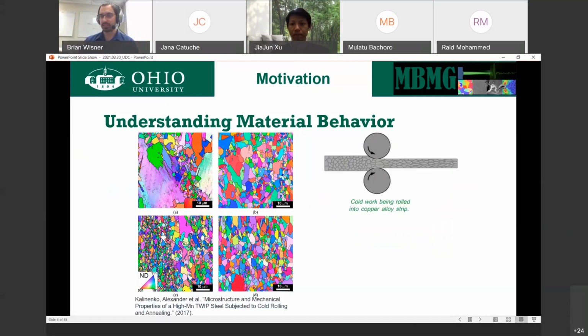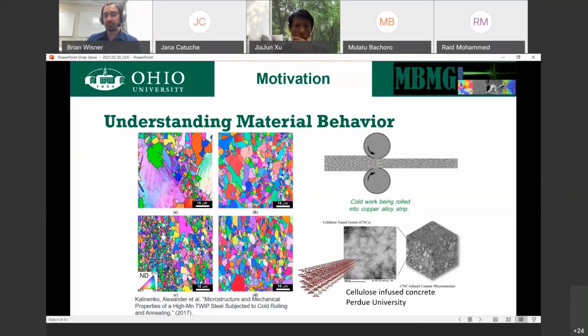Some of the ways that we commonly do this now is in the manufacturing process. We do a rolling process. It's going to alter the microstructure. In the case of cold rolling in particular, it's going to cause us to have elongated grains in one direction. That's useful in sheet, not so useful in a bulk, large structure where you want isotropic properties. But we can control that. We can even go so far in some concepts that we can actually, in cement, infuse cellulose.